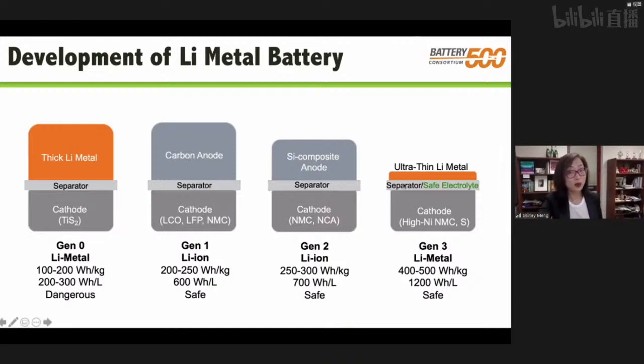So today, when we build the third generation, or second generation, lithium metal cells, you can actually see that we can afford to put a very thin layer of lithium metal because the new electrolyte discovered by Pacific Northwest National Lab enables us to deposit and strip lithium with very high efficiency. So in theory, you can have anode-free. But of course, anode-free has other problems. I will just say we just need ultra thin lithium metal because most of the lithium will be contained in the NMC side.